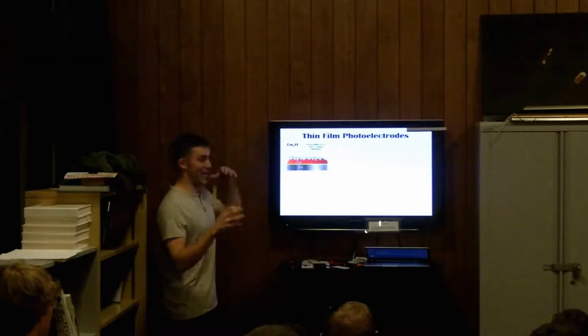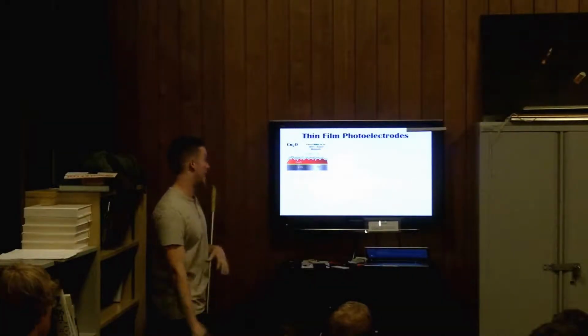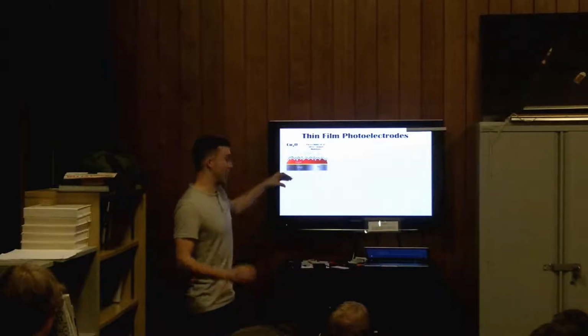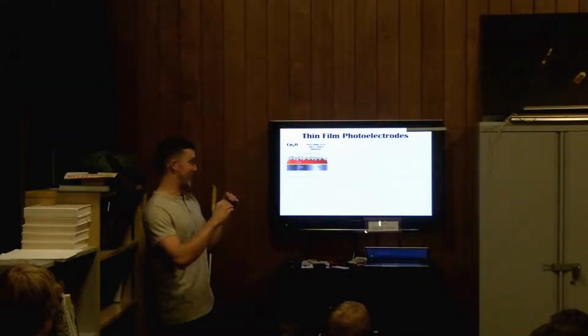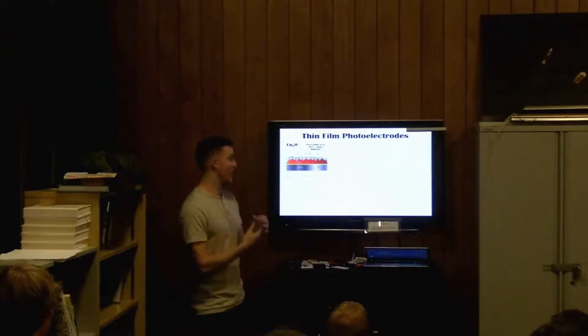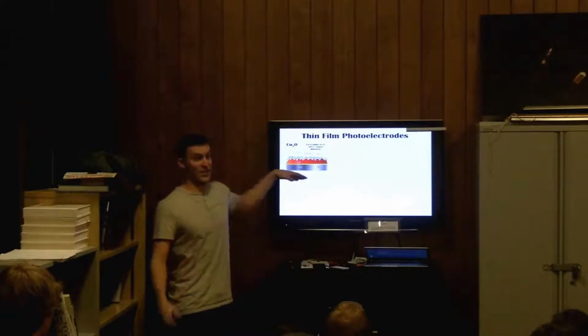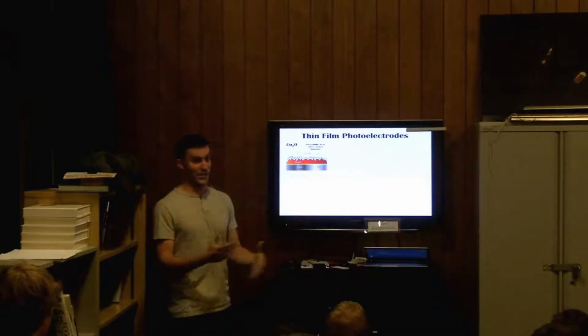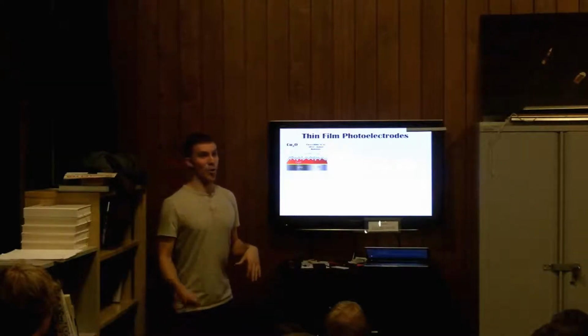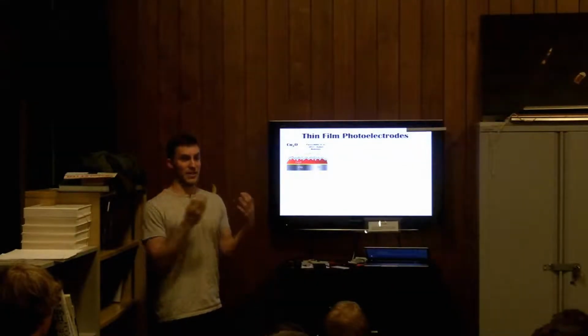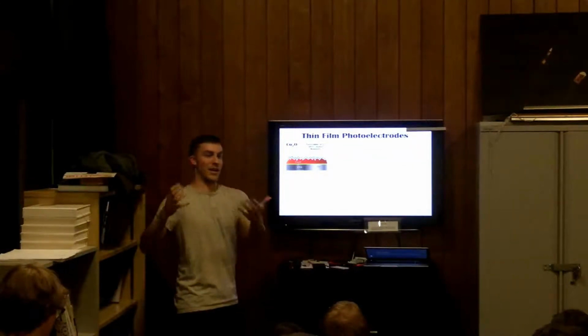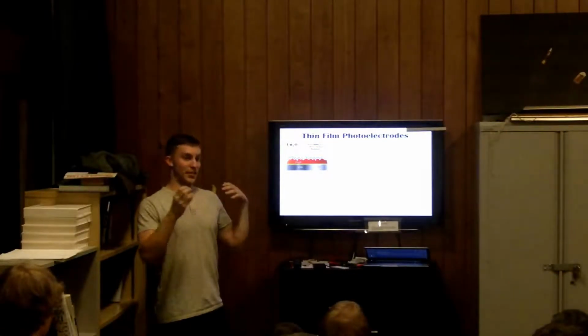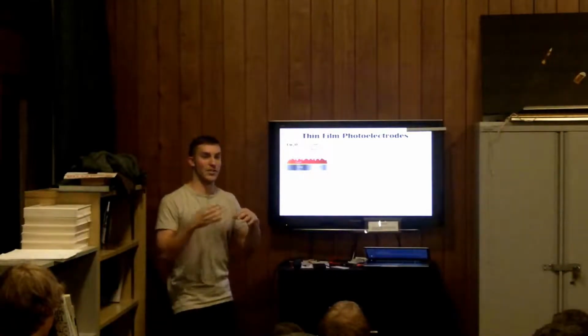And so here's kind of a schematic of what that cuprous oxide electrode actually looks like when we prepare it. First we have essentially a glass slide that's been coated with a transparent conductor. In this case it's FTO, fluorine doped tin oxide. And we want that transparent conductor because we need to be able to allow the light that isn't absorbed by our material to flow through in order to impinge upon the other electrode or do other useful work.